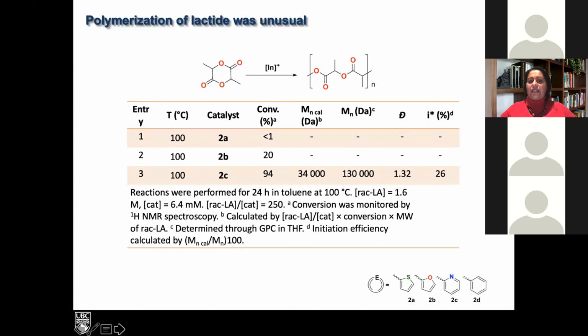The epoxide polymerization is fine, but the thing that Tutura found that I think is really interesting is that he was able to show that compounds 2A and 2B, the ones with sulfur and oxygen donors, were not very reactive for lactide polymerization, probably because the lactide would just coordinate to them and sit there. But the nitrogen donor, the pyridyl donor, was reactive. It wasn't super reactive. This is at 100 degrees, but the conversion was 94%, and we were getting really high molecular weights. And the question was, what is going on in these systems?